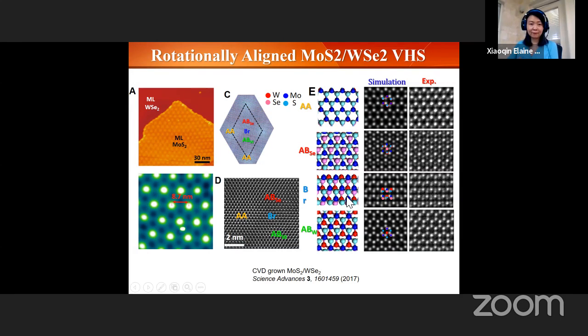And anywhere in between, I have not perfect alignment, either with the center or the atom. So I would naturally expect this gradual atomic alignment. The picture I show you on the left is taken by STM measurement, scanning tunneling microscopy. This is topography, but this picture is basically a measurement of density of states. So I actually have this checkerboard where I have pockets where electrons tend to go. Okay, so there's a higher electron density there. I'll show you more data to back up why that is the case.